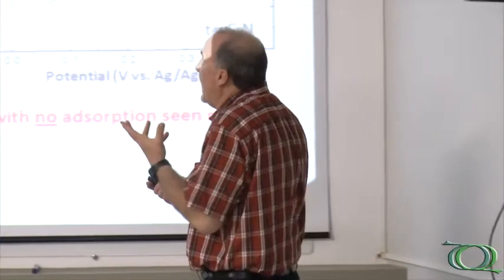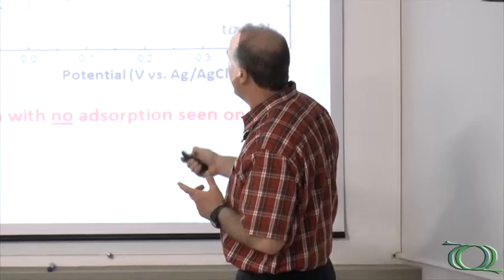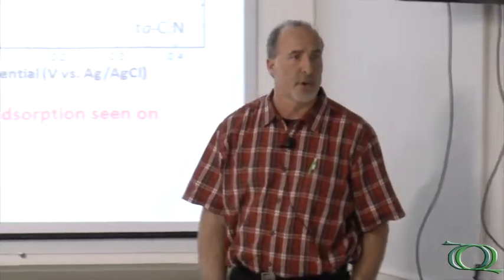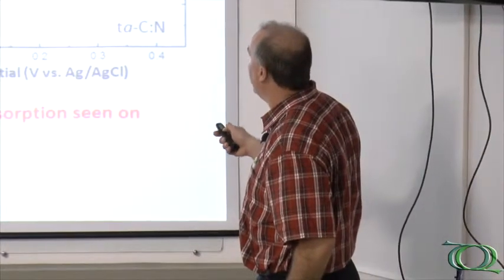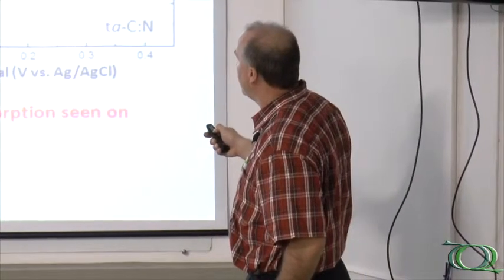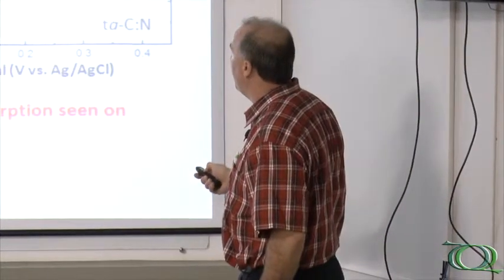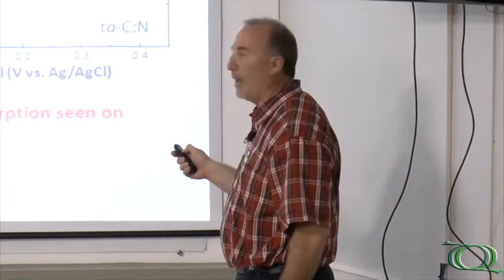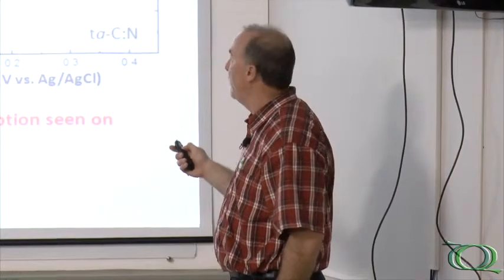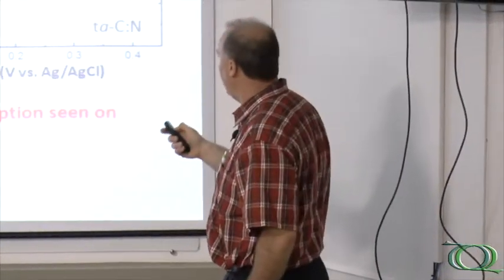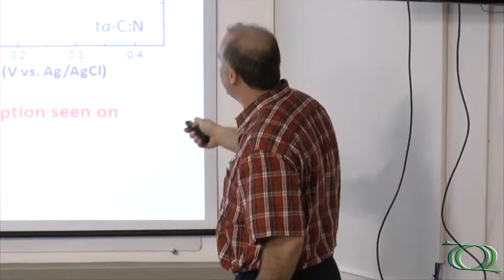So we do these experiments on a ta-C:N electrode with methylene blue, which is a very strong adsorbate on glassy carbon. The dashed curve is when it's in solution — there's the oxidation wave and the reduction wave, a nice reversible system. The measured peak current is about 0.14 microamps, and the calculated peak current for a diffusion-controlled process is virtually the same: 0.15 microamps. If you take that electrode that was exposed to methylene blue, wash it, and put it in a clean electrolyte, you get back almost exactly the same curve with virtually no signal — no adsorption on this surface.